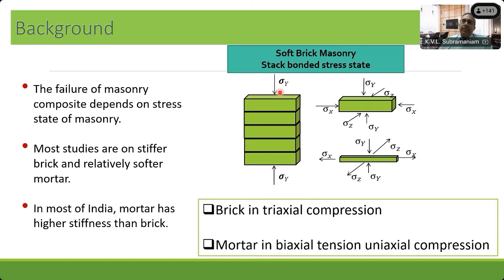When you're dealing with masonry, typically you're dealing with a very complex state of stress in the constituent materials, the brick and the mortar. And therefore, if we really want to model this, we need to understand what stress state is produced in the two materials and be able to then understand which material would fail first. Both these materials are weak in tension. That's one thing we need to remember. And both these materials are what we call brittle materials. So both brick and mortar are brittle, which means that they are stronger in compression, weaker in tension. And ultimately, the compressive failures in both materials are essentially a crushing type of failure.